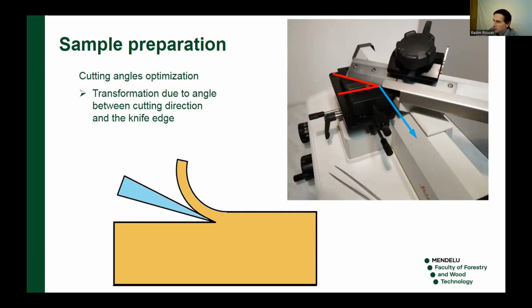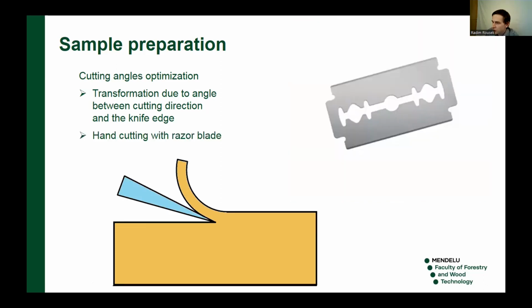Unfortunately, this microtome doesn't allow to set the angles even lower, but there is another option. If I want really a very good surface, I simply use the hand cutting with razor blade. It allows me to make the clearance angle practically to be 0. I can't make, of course, a big surface with such a razor blade, but for the electron microscopy, small, smooth surface is enough.